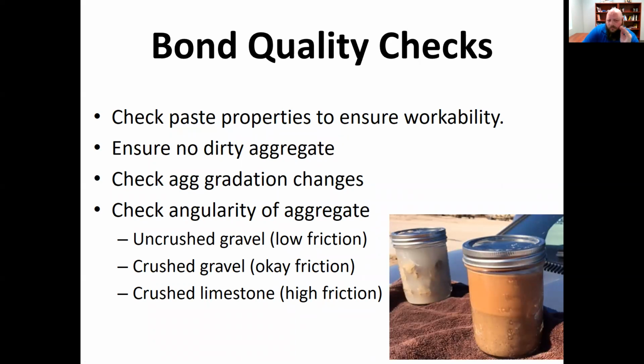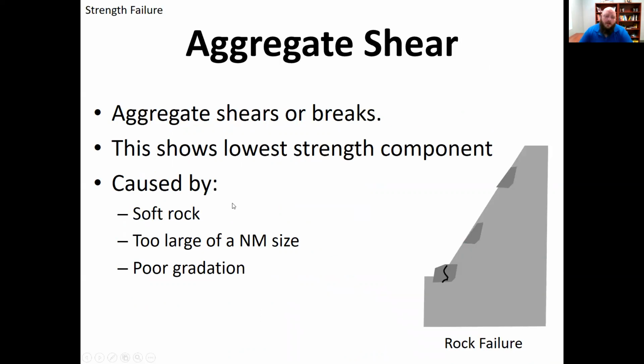You need to realize where you're having the bond issue at. Another thing is talking about aggregate shear. So typically what happens is if you have a soft rock or a gradation that's really almost like one size, you may start seeing some aggregate issues, or even if maybe your mix's nominal maximum size is too big, it'll just shear it. So you've got to be kind of careful.